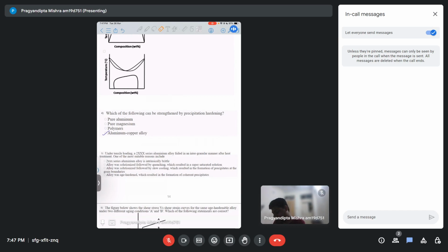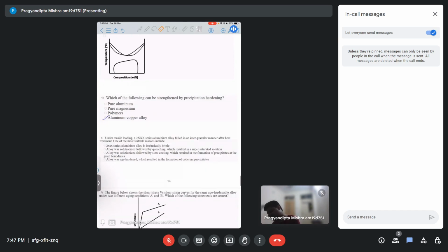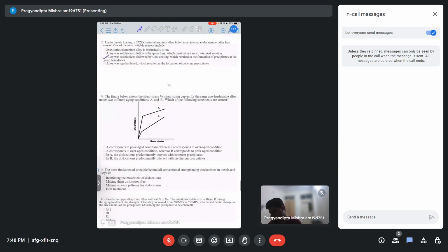Next option, alloy was solutionized followed by slow cooling, which resulted in formation of precipitates at the grain boundary. This is correct. If you do slow cooling, you will see formation of precipitates at the grain boundary, which will lead to intergranular failure. And finally, alloy was age hardened, which resulted in formation of coherent precipitates. That is wrong. Moving on.